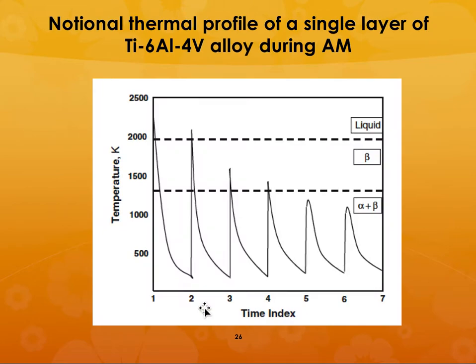For example, this is the thermal profile of a single layer of Ti64 during additive manufacturing. So this is in degrees Kelvin. This is the temperature at the top layer, and as you go away from the melting point, I mean from the topmost layer, you're going to have some kind of a gradient in temperatures. So that's going to have some kind of a residual stress and all kinds of associated problems with that.